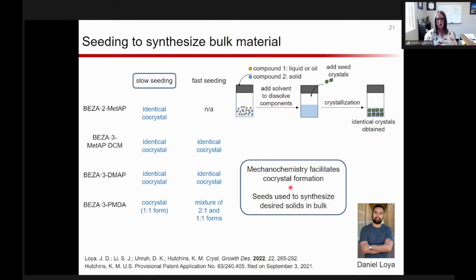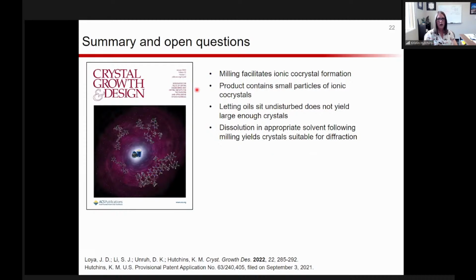And so we've been able to show that mechanochemistry does facilitate this co-crystal formation. And then once we have those seeds in hand after the milling, we can actually go back to solution and make the material we want in solution methods as well, where we cannot do that without the milling step. And so we were able to nicely have the cover of Crystal Growth and Design in January of this year, which was designed by my graduate student, Daniel.